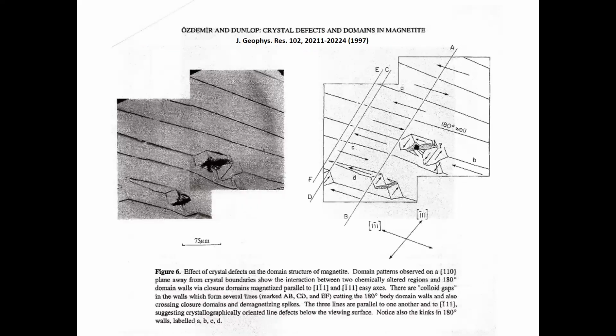Then another 2 years passed, and Özdemir looked into the effect of stress on domain structures. So getting a little dirtier, voids in the crystal, imperfections of various sorts. The lines here, A, B, C, D, E, F, are gaps in the colloid patterns, which show underlying line dislocations. So first evidence that the dislocations really are down there and presumably are acting to pin domain walls.